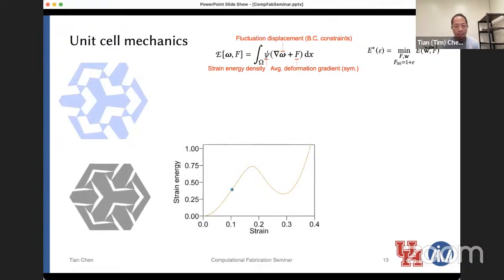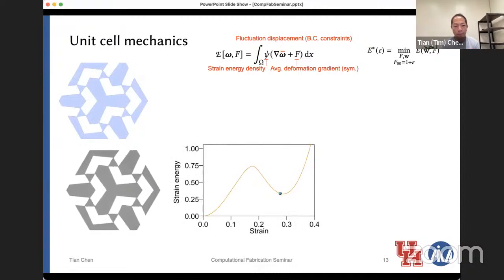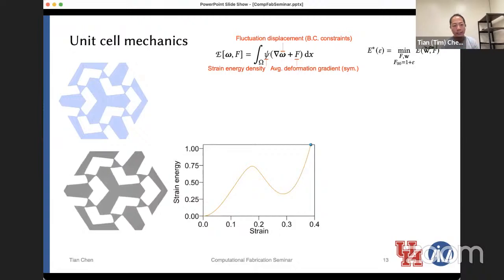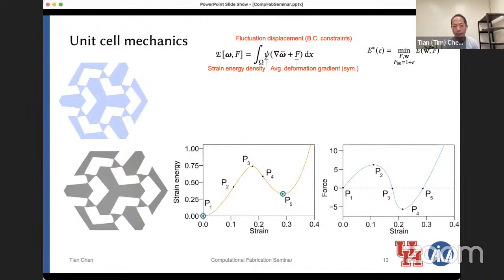So here's the strain energy versus strain diagram of the simulation of the FEM. You can see there are two local minima in the strain energy landscape, thereby indicating there are definitely two stable equilibrium states. And since we can easily differentiate this curve, we get the force versus strain diagram that we typically see of a bistable system. So now what do we pick, right?